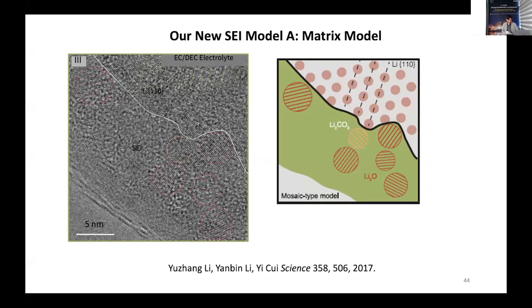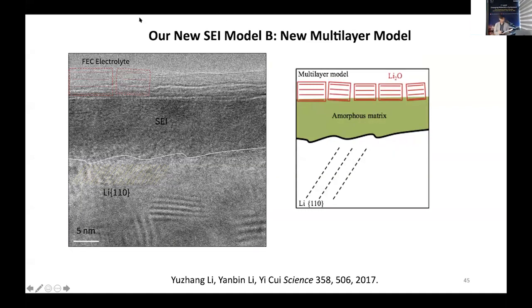We found, using EC and DEC electrolyte, you can see on the left-hand side the metallic lithium on the top, and this white line indicates the interface between SEI and lithium metal. The structure looks like inorganic nanoparticles embedded in an amorphous matrix. Presumably, that's more of the organics right there. So this is more like a mosaic model, but we like to use a term called matrix model to describe it. This is using ethylene carbonate, diethyl carbonate electrolyte, but as soon as you add fluorinated carbonate as an additive, which is commonly used in batteries, the whole SEI structure changes to a multi-layer model, with lithium metal at the bottom, then an amorphous layer. And on the top, you see this beautiful lattice fringe. That's the inorganic lithium oxide on the top. So it suggests a multi-layer model.